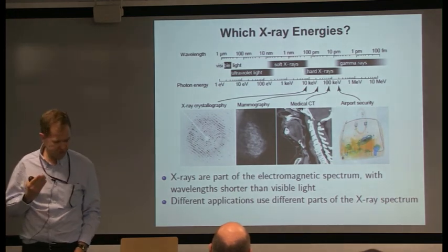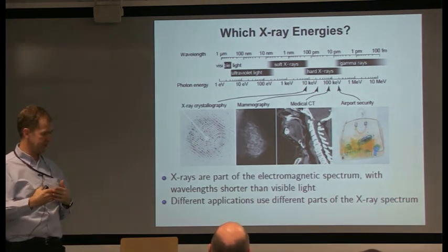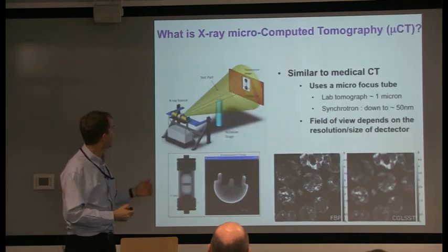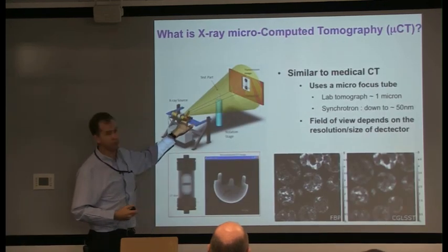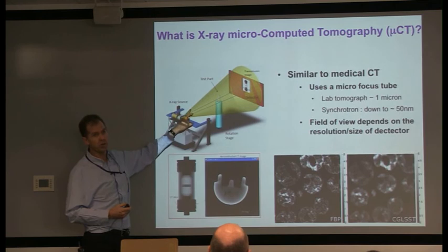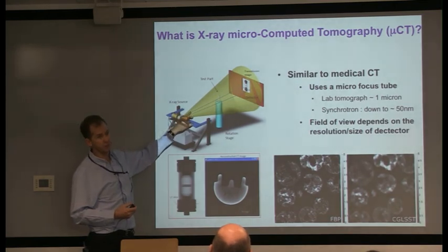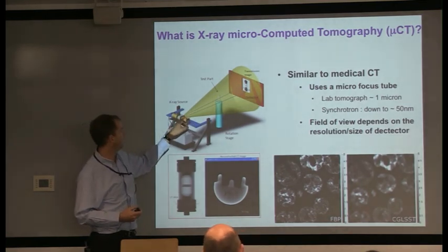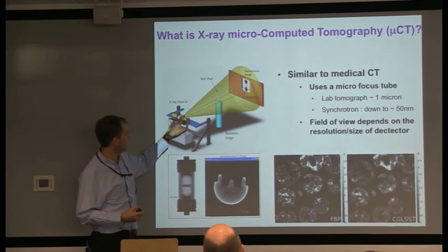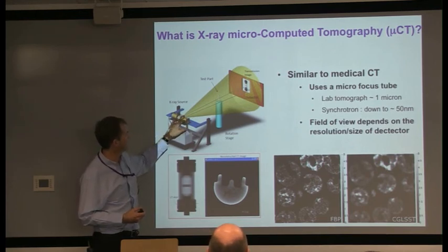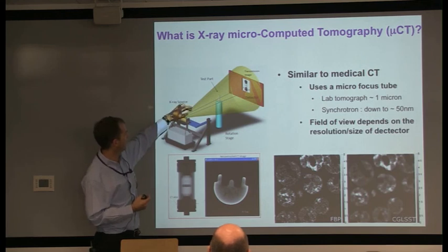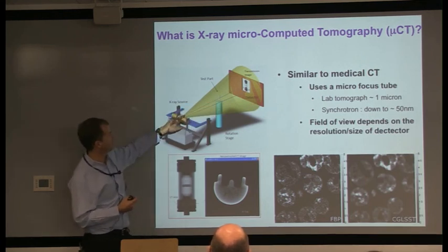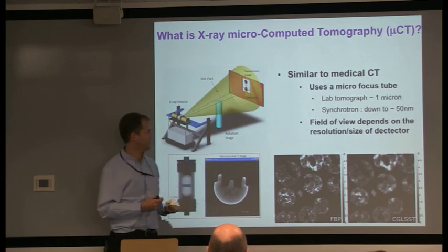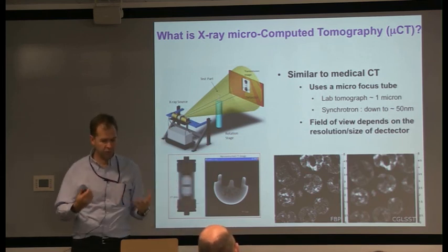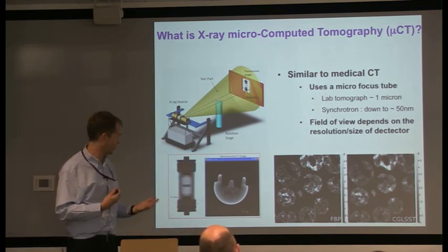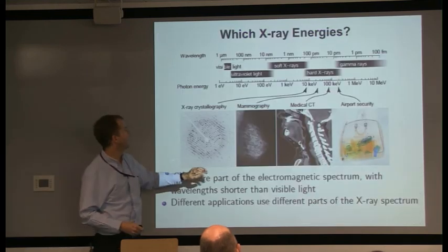So that tells you the size you can get is how close you can get the sample to the point. And of course, when you have the sample inside a radioactive containment, you can probably only get it within a few tens of millimeters. You also have to know that this is an electron beam hitting a target, so you have to have something non-magnetic if you're coming really close. If you want high magnification, you bring it close to here. Low magnification, bring it close to your detector. Relatively simple, continuously variable magnification, which is great, which you don't get at a synchrotron.